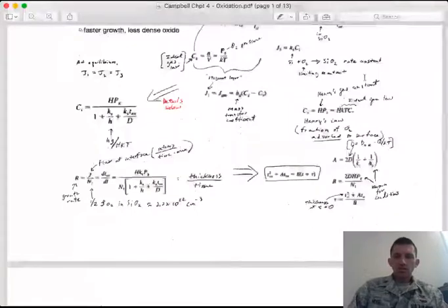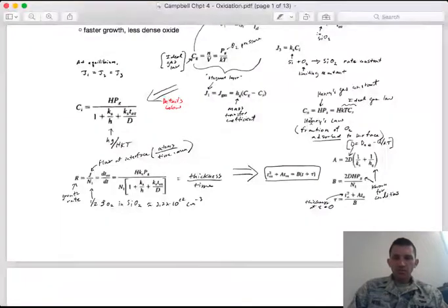And here in Henry's law, we have Henry's gas constant, which is a proportionality between the concentration on the surface and the partial pressure of the gas. And so using the ideal gas law, we can substitute partial pressure for kT and then the concentration. So this will be our third equation for the proportion of the oxygen that is adsorbed to the surface.